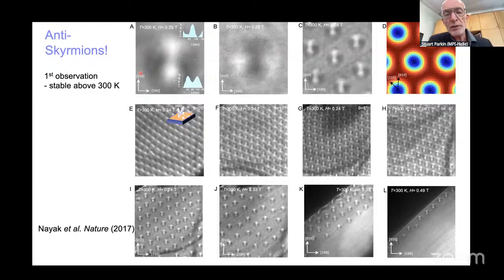This is a very interesting material. The Heusler family actually has a lot of materials. And what we demonstrated was these antiskyrmions are formed in arrays, hexagonal arrays. And by applying magnetic field in the microscope, we could eventually cause these antiskyrmions to disappear at high enough magnetic fields when they form a uniform magnetic state.